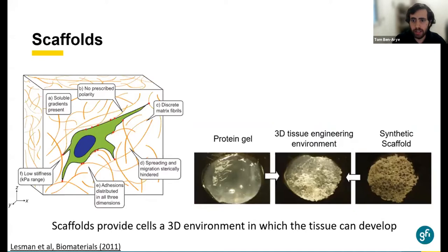We use scaffolds in order to grow cells in a 3D environment that mimics the 3D environment of the tissue. The scaffolds need to be porous, have mechanical strength, and be cytocompatible, not harm the cells, so the cells can survive in them. An optimal scaffold will have both the porous structure that we see here, which provides the mechanical cues and holds the shape of the tissue, as mentioned before by Schumacher, and the protein gel that provides the biochemical cues and helps cells grow naturally in the 3D environment.